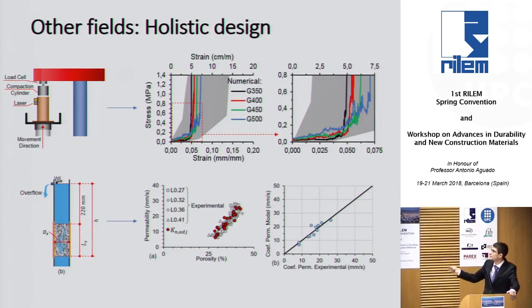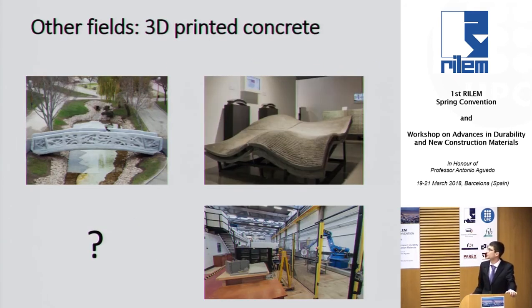Right? So here you see some results of the compaction process. So the strain during the compaction and the stress applied. The graphs are marking, in this case, what we simulated, and the gray area, the testing, the experimental program. And here you see permeability, for instance, depending on porosity. The red dots are the simulation, and the gray dots are the experimental results. So we can get very good fits with this type of holistic vision in which you simulate the whole process of production and the performance of the material.